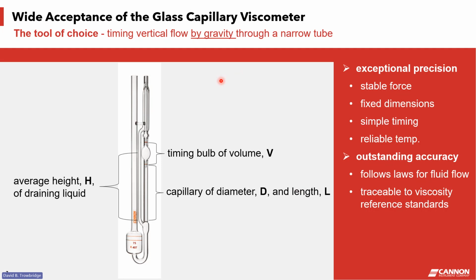So this simple design gives exceptional precision. This was the favoring aspect of the instrument, and it had a stable force. The gravity was very reproducible, of course. At fixed dimensions, this was rigid glass, so there weren't fluctuations in these important dimensions that are mentioned here. Also, the timing was simple. You just watch the meniscus drain past the lines on the glass. And you have the ability to control the temperature very well because of the shape of the viscometer, a U-shape, you can immerse it into a bath and control the temperature to a fraction of a degree. Also, there was outstanding accuracy because the flow in the capillary, as I said, was just simple laminar flow that followed basic laws of fluid flow, and also measurements were traceable to viscosity reference standards.